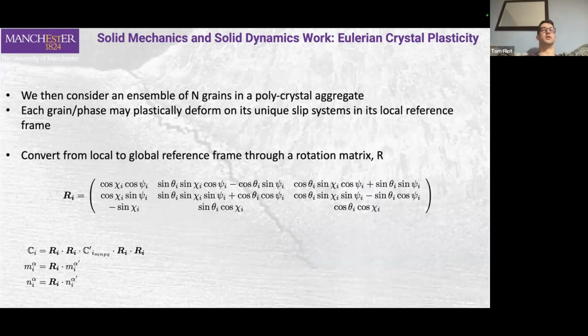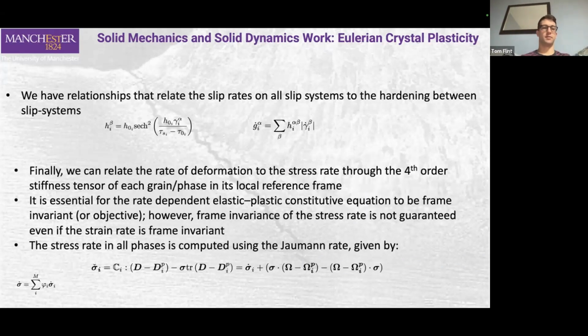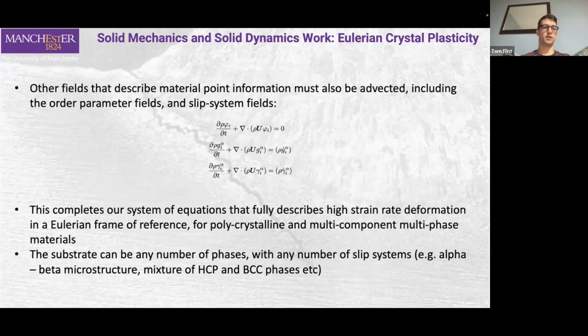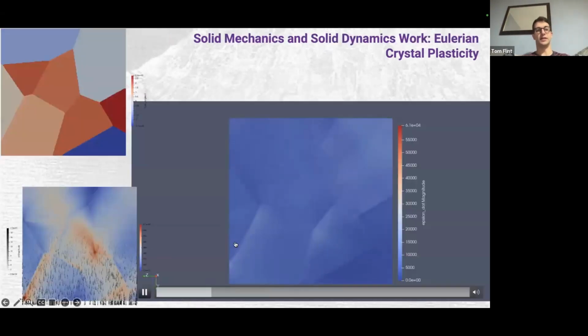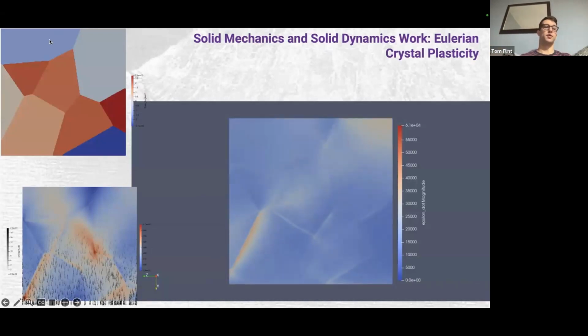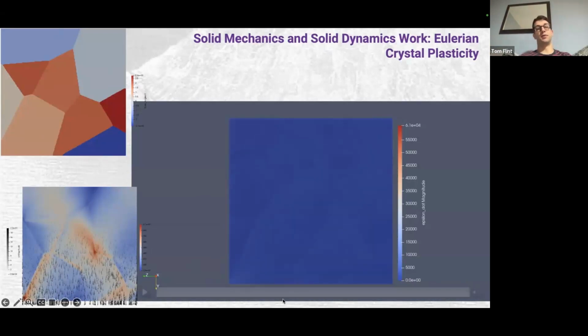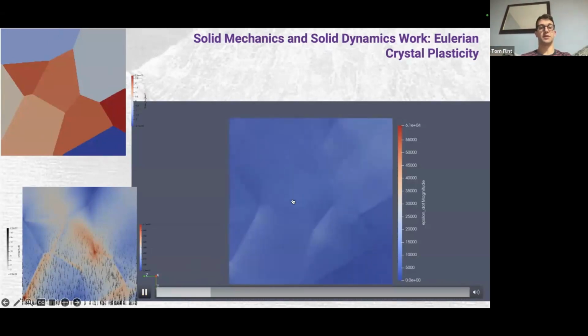So again, the intention is to make this tool open source. Longer term, it's quite a lot of work to make these things open source, as people probably understand. But again, a lot of equations, pretty dull, really. But here's an example of it going on. I guess this is what might be of interest to people. So we have this initial microstructure here on the left hand side. We apply some shock, and what you're seeing is the shock wave propagating through that polycrystal microstructure, bouncing back off the domain, and then we're getting some localization of strain.